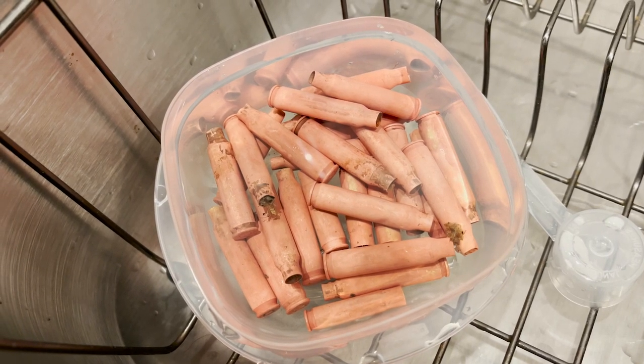How thick is that patina on those casings? Generally speaking, it's accepted that copper patina goes to about two thousandths of an inch. To put that in perspective, the thickness of your case at the case neck should be about ten times that thickness — so you are good to go. You're not eliminating very much from that surface at all. Now, if you do this repeatedly over time, that could be a problem. Remember that a patina is not a degradative process — it's actually a protective process, and it's one of the properties that we go for when choosing brass.